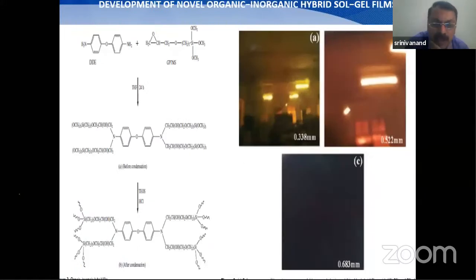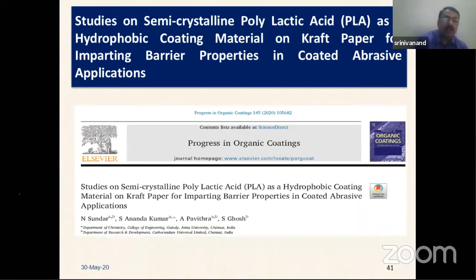Similarly, we were able to make some transparent films by changing the silica content. We were able to obtain completely transparent material to completely opaque material. This is also carried out in our laboratory. In the recent past, we have published our findings in one of the reputed journals, Progress in Organic Coatings, which is in Web of Science, whose impact factor is 3.6.